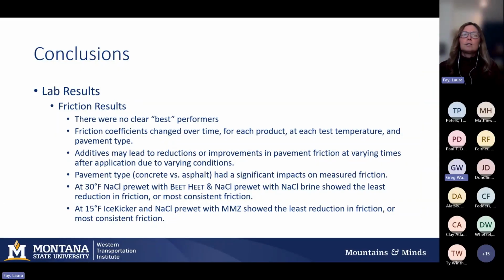And with the friction results, I think what can be seen is that there was no clear best performer. We couldn't rank one performing better than the other. What we could say is that the addition of de-icers creating liquid on the road reduced friction, which we all know happens, and that the products each either added value or reduced friction at different times during testing. But after an hour, they all kind of achieved a reasonable friction value.